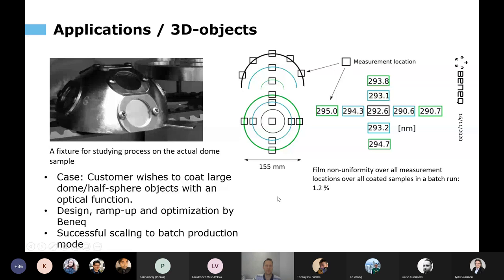Another example, and also an example of the practical challenges that we have to deal with, is a coating for optical domes. In this case, 155 millimeters in diameter, like a half of a ball. Again, the target is to make a uniform coating on that, so again an AR coating. The difficulty is, of course, to coat it, but also to measure it. To be able to tune the process, we need something that we can measure, and it's rather difficult to measure on such a curved object, but it's easier to measure on flat, smaller samples.